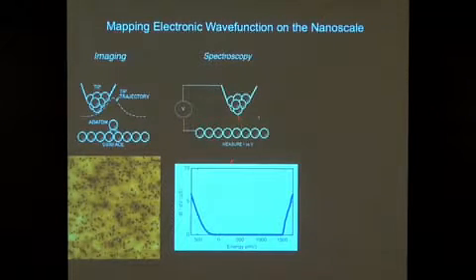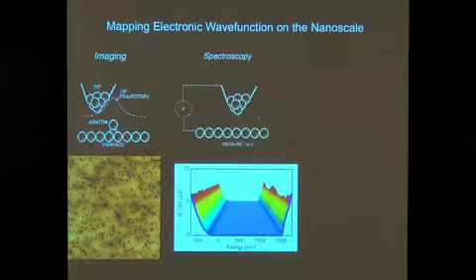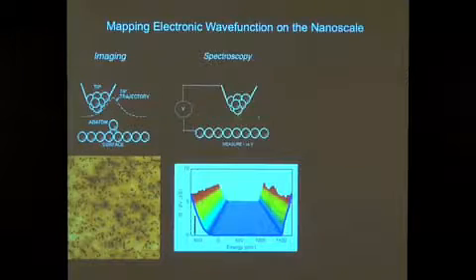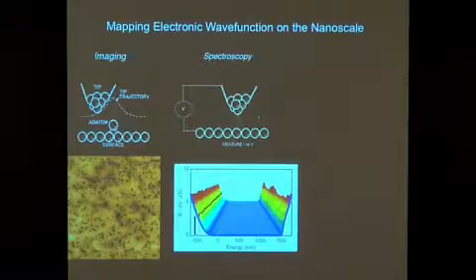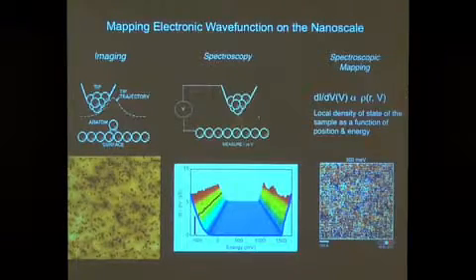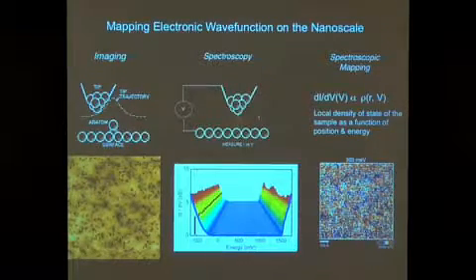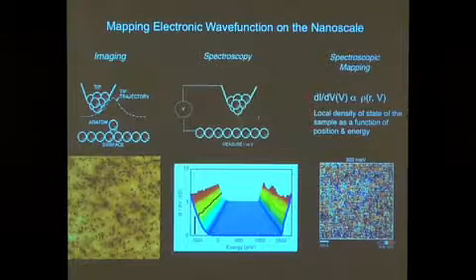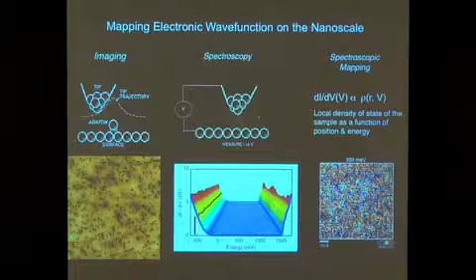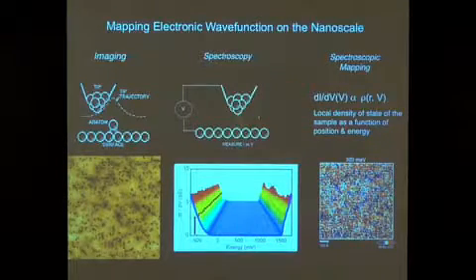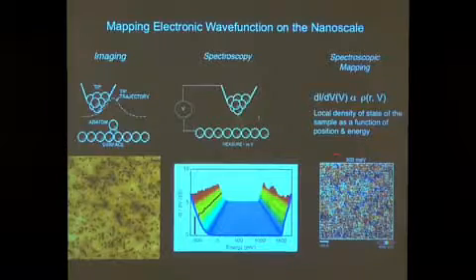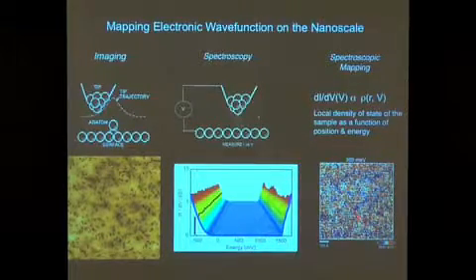But usually what we use it for now is to look at what electrons are doing in the sample, to measure the rate at which the electrons tunnel between the tip and the sample as a function of energy. And of course, the power of this technique is you can do it as a function of position. And you can basically interrogate what electrons are doing both as a function of energy and as a function of position in your sample. And I'm going to show you a lot of movies which basically look at, if you like, the square of the wave function as a function of energy of the electronic state in your sample, and analyze what the behavior of electronic states are from these type of data. Okay? So these are basically energy resolved maps of the electronic states in the sample.